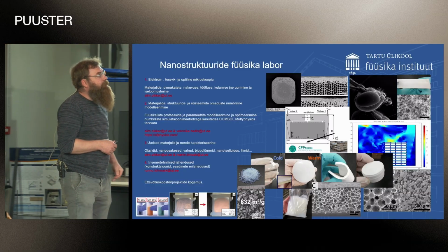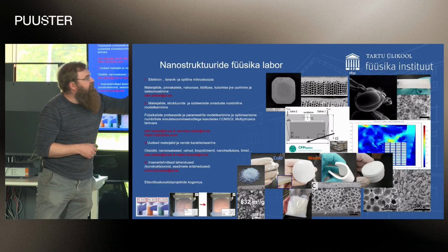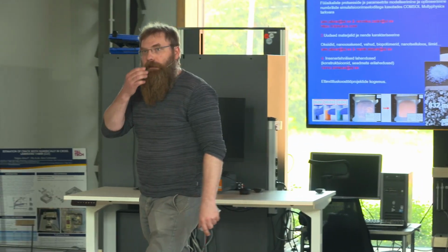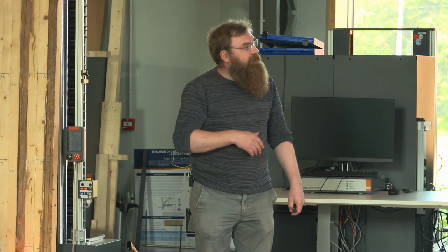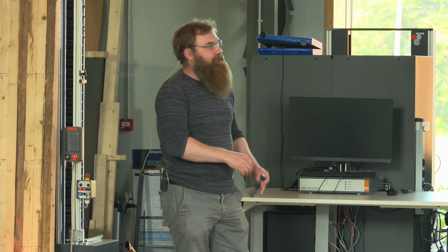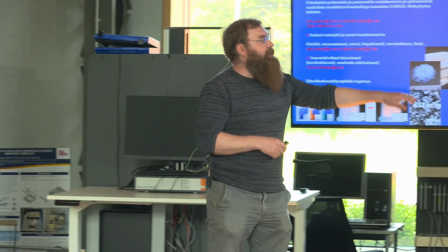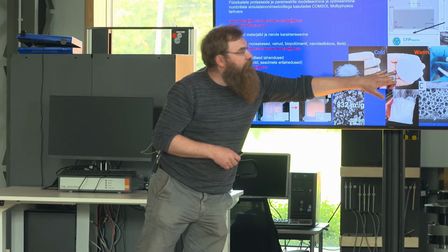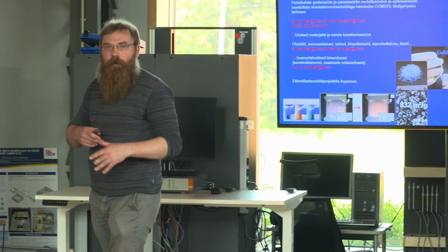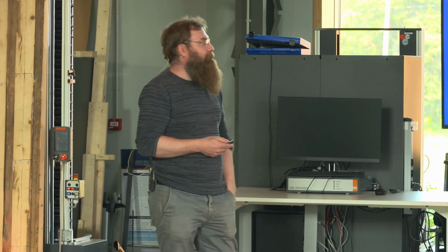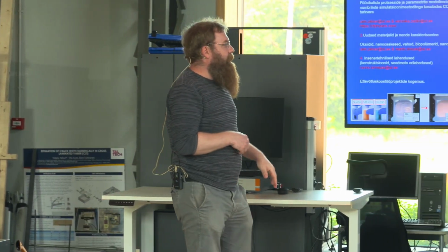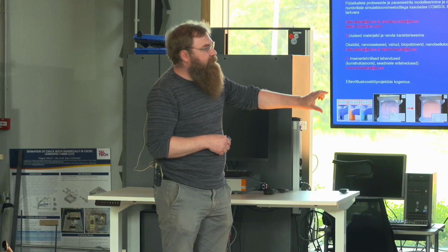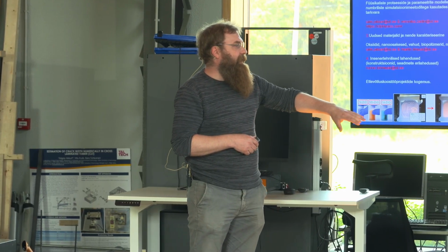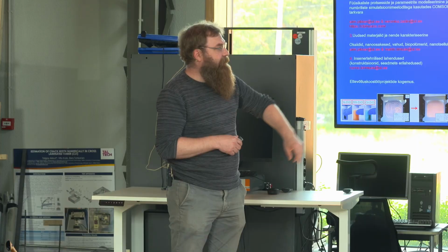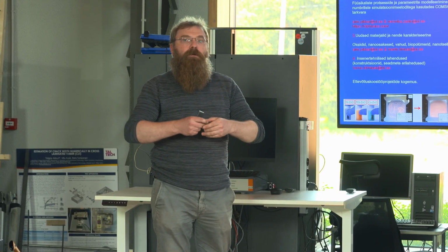We have here a material that changes from transparent to opaque thanks to material properties and microstructure and nanostructure. And this switch of transparent material to opaque material comes from temperature shift, and it's a very fast acting material. So we did a lot of nanostructures, microstructures, which sense, let's say, magnetic fields or electric fields, which gives an optical signal.